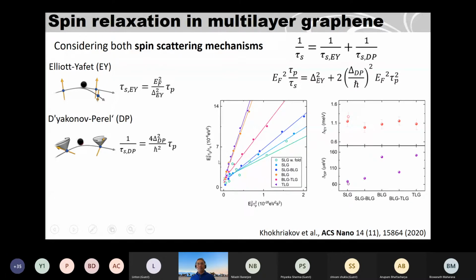And if you fit these lines for different layers, single layer graphene and bilayer graphene, and then the boundaries and tri-layer graphene and graphene with fold. So they have a little bit of difference in spin relaxation properties, but what you can find is that by fitting these ones, you can find out the strength of both Elliott-Yafet and Rashba here. And as you see, this is in millielectron volt, the Rashba. This is the momentum scattering, around 1 millielectron volt.